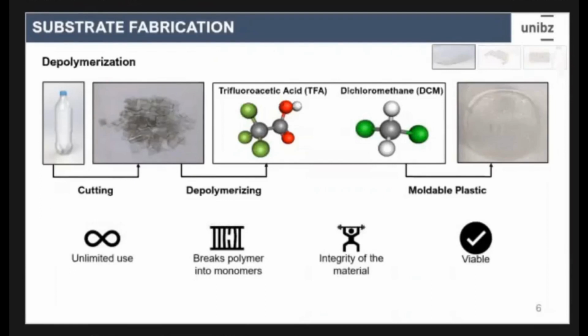We break the polymer into monomer molecules. The integrity of the material is not lost, so the plastic will be strong once it is fully recycled, as strong as it was before, and it's a viable solution to the recycling problem that we have these days. Now, after the depolymerization, we have to repolymerize again to create the plastic that we want.